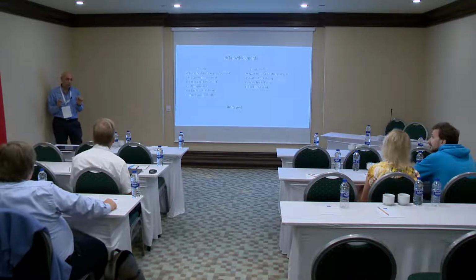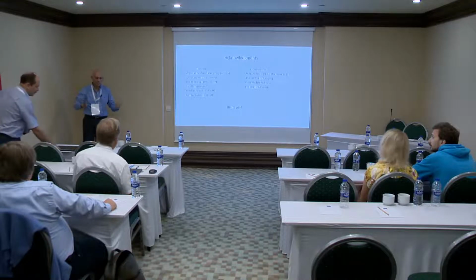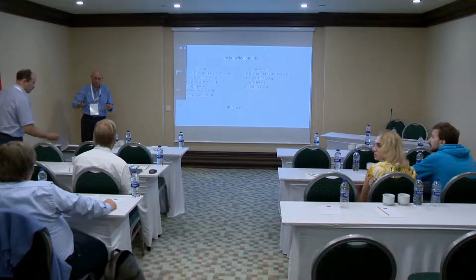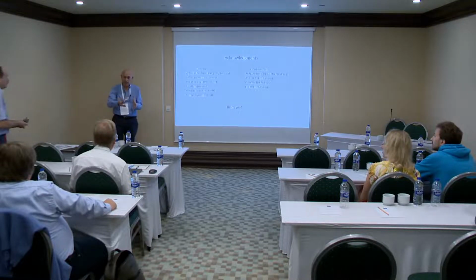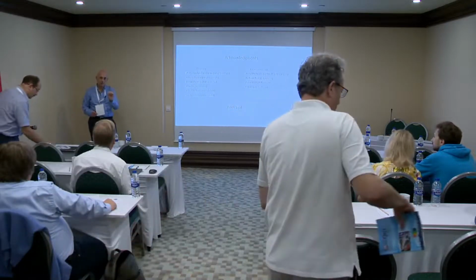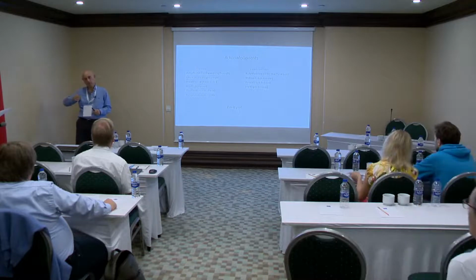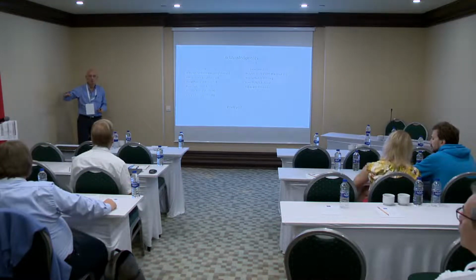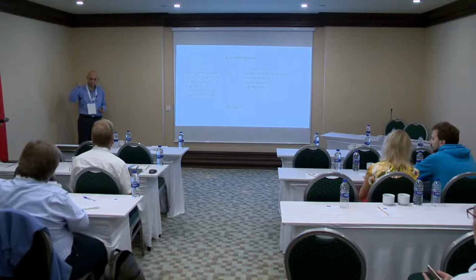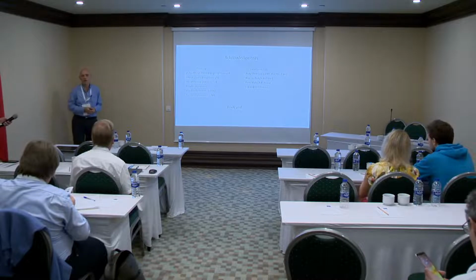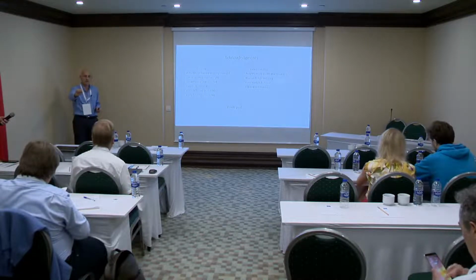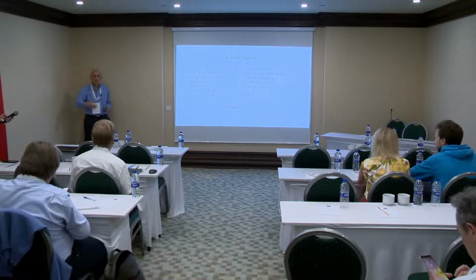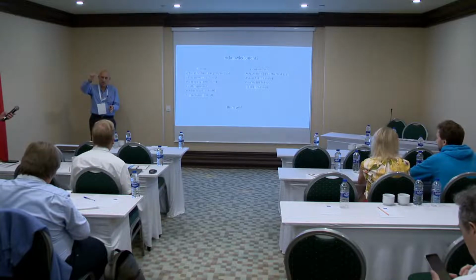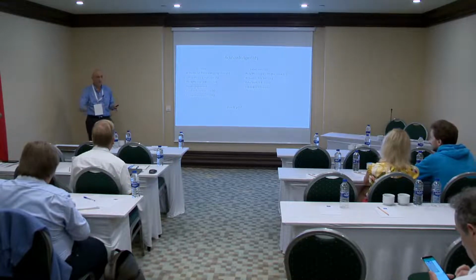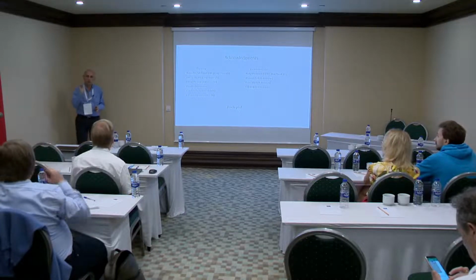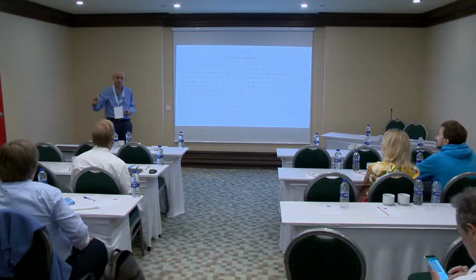What we were trying to do is this: because DFT calculations do not take everything into account, many things will get renormalized. But if you have a sensible magnetization, that more or less will be associated with real, not exactly these values, but reasonable values. And you see as a function of that the Fermi surface. It conveys the message that if you take the real thing, modify your Hamiltonian and the way you do the calculations, you should get exactly the same thing. So we wanted to get it qualitatively at that point, not relate the numbers exactly.